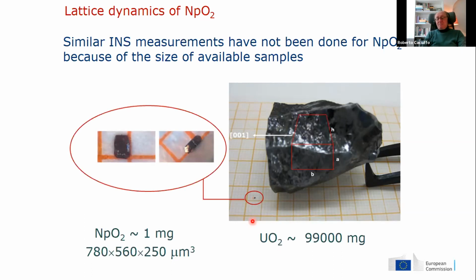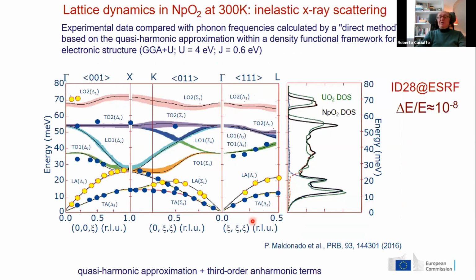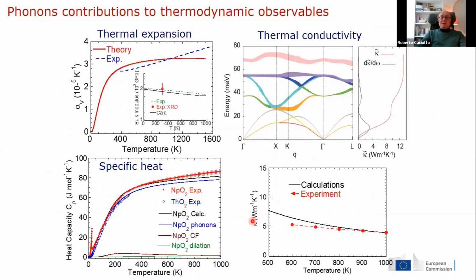Neptunium dioxide has a mass of a milligram. The crystals for plutonium dioxide have a mass of 1 microgram. Still, this is enough for inelastic X-ray scattering. These are the dispersion curves that we measured on ID28 for neptunium dioxide, and they were good enough to benchmark direct method calculations of the phonon frequencies and anharmonic calculations that then have been used to model the phonon contribution to several thermodynamic quantities of practical importance: thermal expansion, specific heat, thermal conductivity.